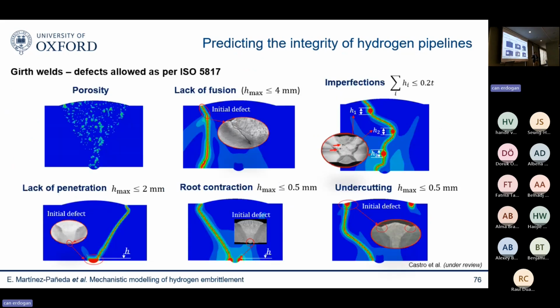So, for example, we went to the welding standards, and the welding standards will let you pass your weld with certain defects, some admissible defects. So we incorporated all those admissible defects that we know exist in those natural gas pipelines because the standards allow for it, and we quantified whether they were problematic in hydrogen or not. And this is something, once you have a model, it's very easy to do, right? You put whatever defect you want, you run the simulation, and you see what you get out.